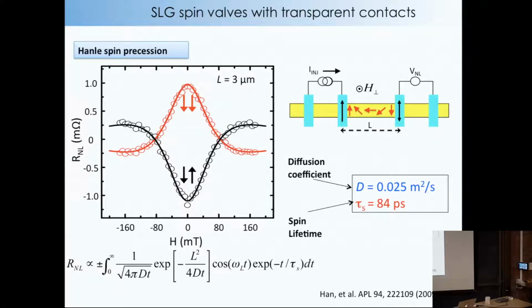So what you do is you apply an out-of-plane magnetic field, and that will cause the spins to precess. And then what happens is that essentially this large signal that you get will start to depolarize. And you can even see some oscillations because these can oscillate. But you get this kind of peak. And for the anti-parallel case, you have a negative voltage, and you'll see a flip over of that first peak. Okay? And once you start seeing these Hanle effects, then you realize, yes, the signal that we're seeing is really